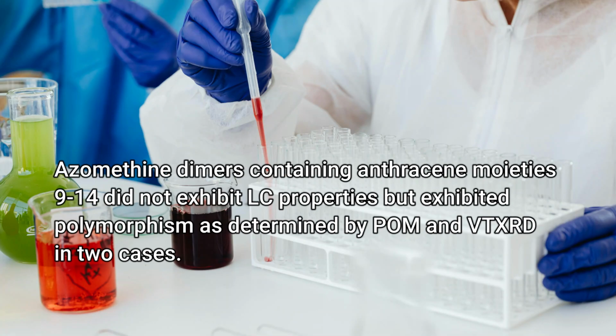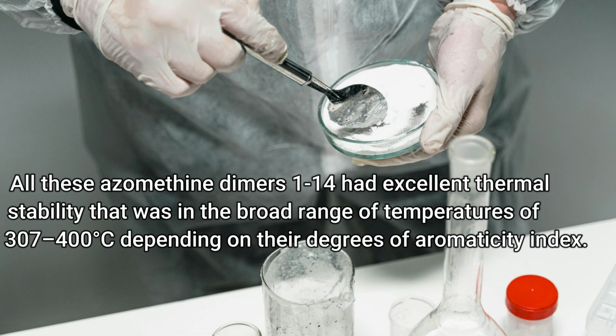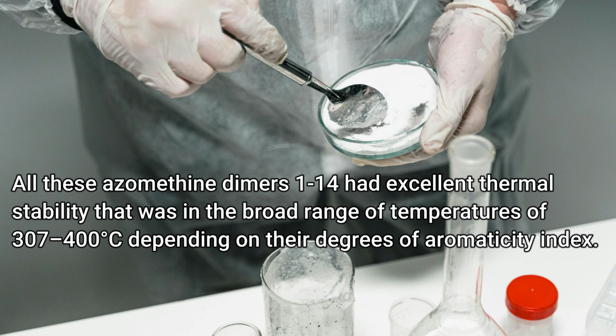Azomethine dimers containing anthracene moieties 9 to 14 did not exhibit LC properties but exhibited polymorphism as determined by POM and VT-XRD in 2 cases. All these azomethine dimers 1 to 14 had excellent thermal stability that was in the broad range of temperatures of 307 to 400 degrees Celsius depending on their degrees of aromaticity index.